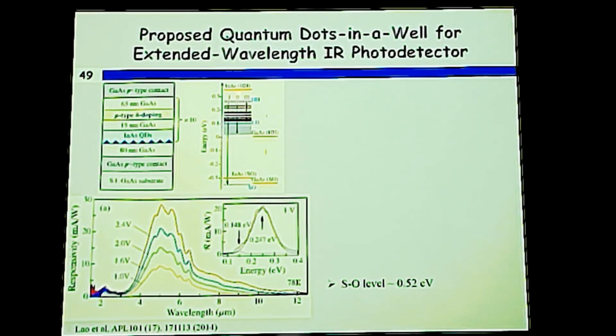The transition from the ground state to close to the barrier gives this peak. There's also another transition from the ground state to the SO band, the split-off band, which gives this peak around 2.2 micron. That is weak because this energy is not a bound state like this. If we make this state a bound state, that will probably become a strong peak. However, 2.2 is not very useful because our interest is in the 3 to 5 micron band.